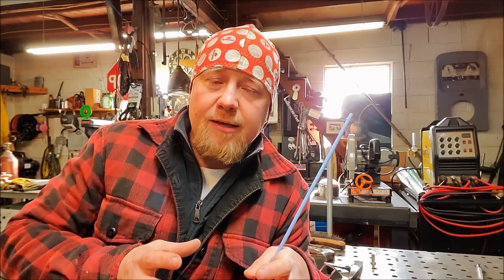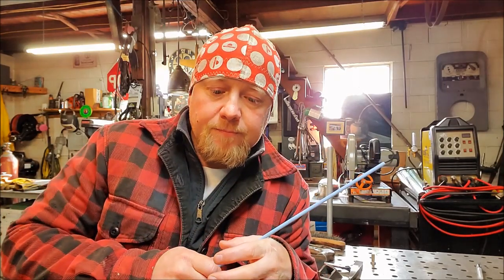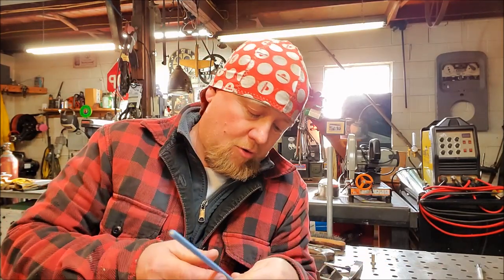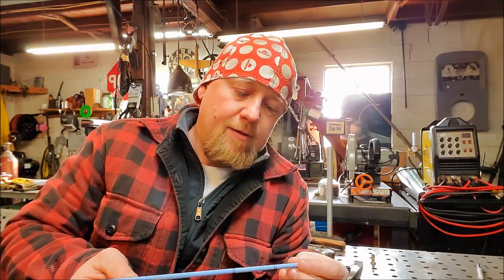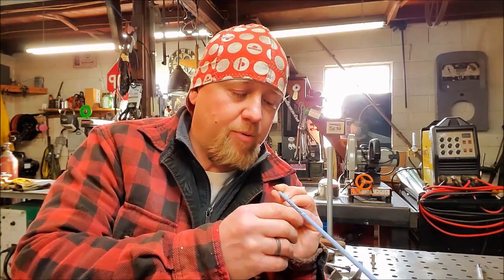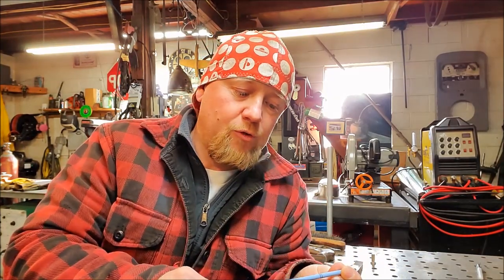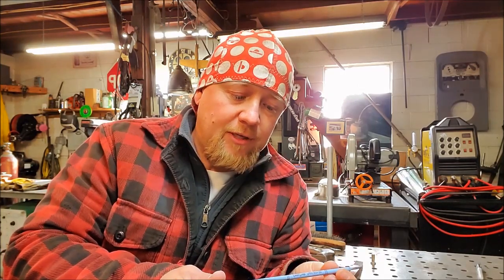So when you're welding onto something hardened like a broken off stud, or any type of hardened wear plate, something like that, that elasticity or the elongation of the weld deposit is huge. These rods, the actual verbiage on the actual electrode, and we put it on every one, says Dyeco Super Alloy SP Superior Dissimilar Steels. So it's superior for welding dissimilar steels.